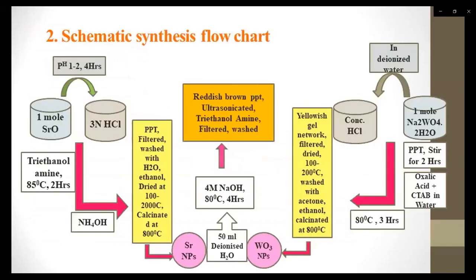This is the schematic synthetic pathway of strontium-doped tungsten oxide nanostructures. Different synthetic conditions are used, with capping agents like CTAB and oxalic acid, 3 normal sulfuric acid and 3 normal HCl, and triethanolamine as a surfactant. So strontium is precipitated and dispersed over the tungsten oxide nanostructures.